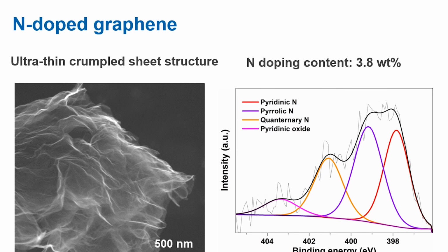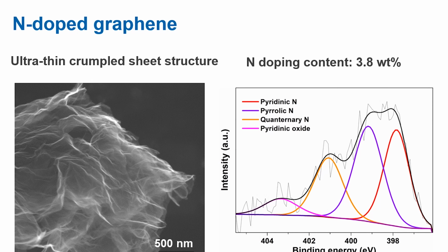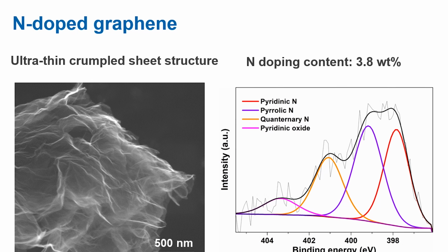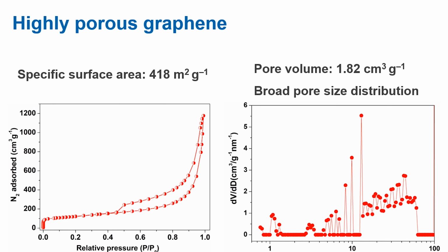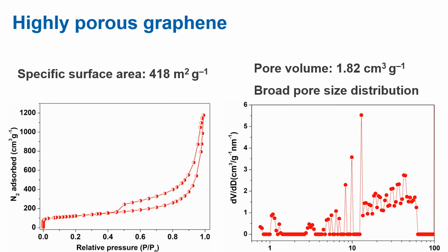From the SEM image, we can see that the nitrogen-doped graphene shows an ultra-thin crumpled sheet structure. And from the XPS results, we can see that the majority of nitrogen exists in the form of pyridinic and pyrrolic nitrogen, which is very beneficial for the chemical adsorption of polysulfides. The highly porous graphene shows a specific surface area of 418 and a pore volume of 1.82 with very broad pore size distribution, which can provide sufficient space for sulfur accommodation and is beneficial to achieve a high sulfur loading.